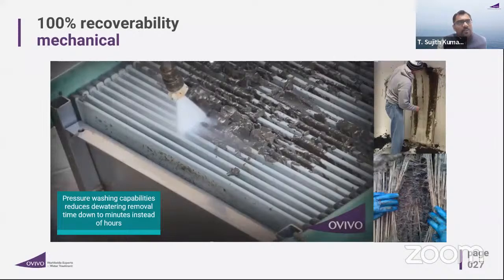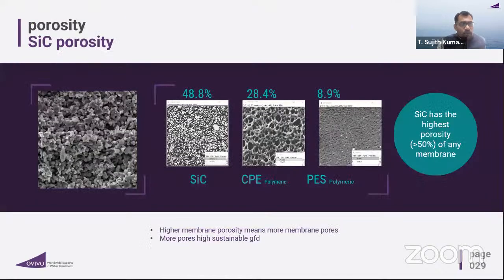Since these membranes are very robust, made out of inert material, you can also do the pressure wash. You take out those membranes, and if dewatered completely, just do the pressure wash with 2 to 3 kg pressure. Absolutely no issue, whereas this is not possible with polymeric membranes. And the porosity: SiC silicon carbide membrane has the highest porosity among the available membranes, compared to CPE or PES membranes. That is the reason we are able to push through more flux, 3 times the flux compared to polymeric.